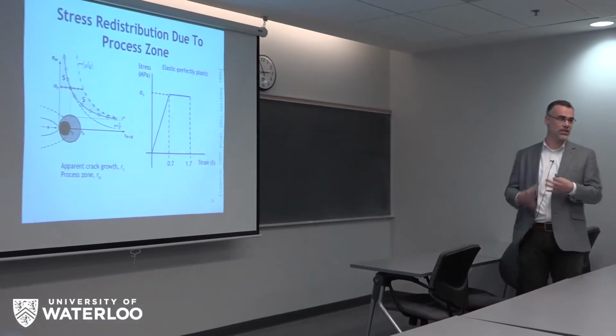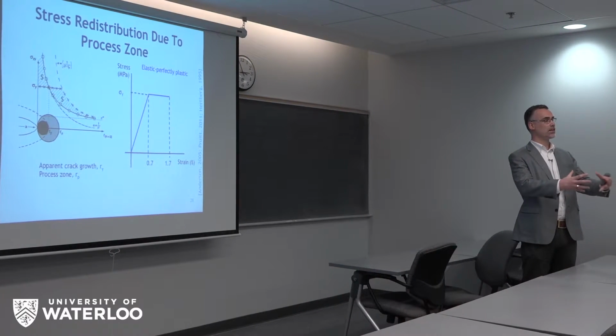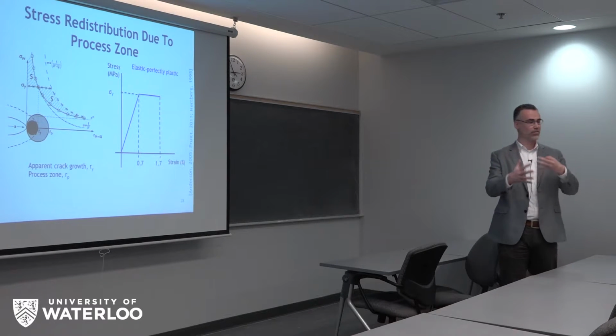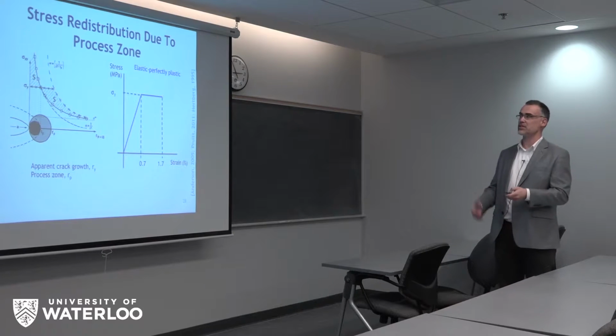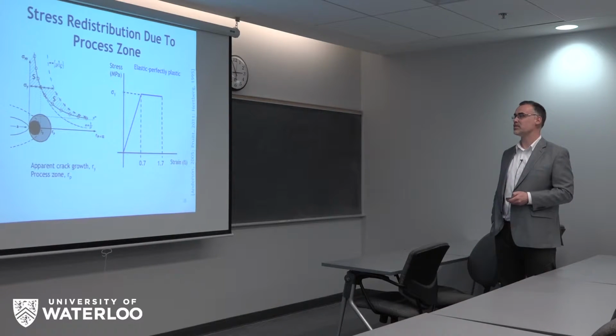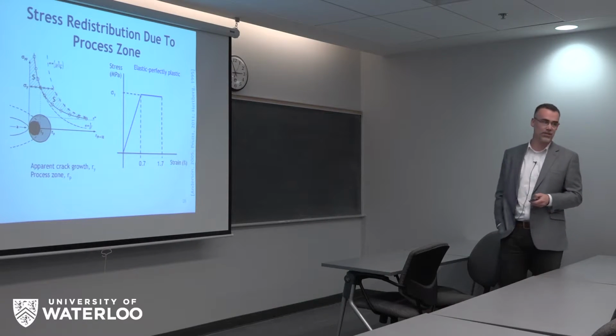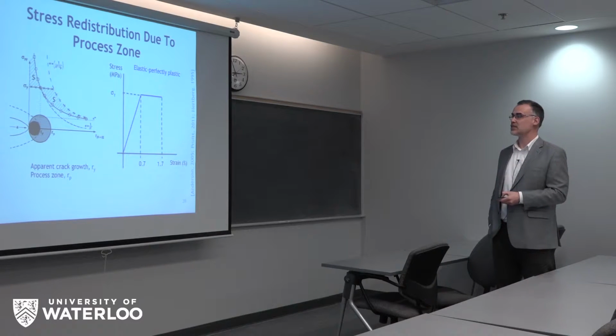Cracks act as extreme stress concentrations, so as you move closer to the tip of a crack, the stress will, in linear elastic fracture mechanics, approach a singularity, infinite stress, which of course the material won't do. In reality, the material will not sustain a stress, say, in a perfectly elastic, perfectly plastic material, higher than the yield stress. And so what happens is you get a region of material in front of the crack that is yielding, and it's called the process zone. And in bone, that's made up of lots of microcracking and plastic deformation, and it results in a redistribution of the stress. And the process zone is large enough in bone that you can't use linear elastic fracture mechanics.